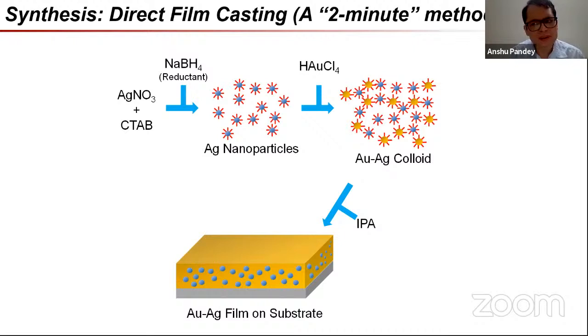But again, the reduction is always being done under strong NaBH4 conditions. So what you are saying does indeed happen. If we do not have strong enough NaBH4, then the ion exchange is a very feasible reaction. And we do get immediate signatures that we are losing silver, and silver ion exchange has very specific signatures, as you mentioned. But because of strong NaBH4, we do not observe that in this case, or at least when we observe it, we know we have to throw away that reaction. It's not a regular occurrence because we make sure we are in strong NaBH4.